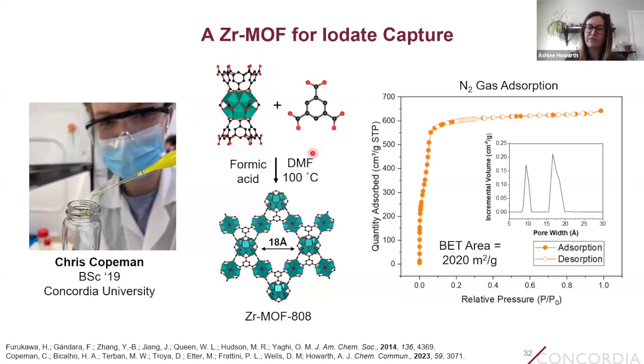This MOF is also made of the commercially available and inexpensive trimesic acid linker, which is great. And Chris Koopman, who is the PhD student in my group that works on this project, makes the MOF using formic acid and DMF at 100 degrees Celsius, and always obtains these really nice type 1b nitrogen gas adsorption isotherms and surface areas of around 2,000 meters squared per gram. This MOF is also extremely stable. It's stable in water for days and weeks, and it's also stable under acidic and basic conditions, so from about pH 1 to pH 9.